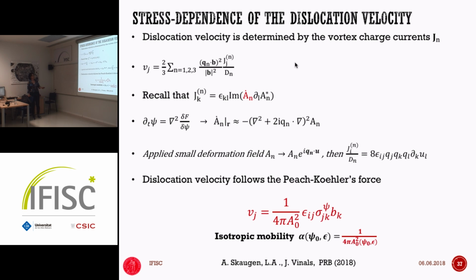So now, in a particular situation where we have some simplification and we assume that the system is infinite, we can approximate this equation, which is quite complicated because it has nonlinearities. But if we ignore all the nonlinearities, the time-dependent evolution of the density field maps into an evolution equation for the amplitude. And next to the defect, I can look only at the linear part, and all the other terms are going to be equal to 0 because close to the defect, the amplitude goes to 0.